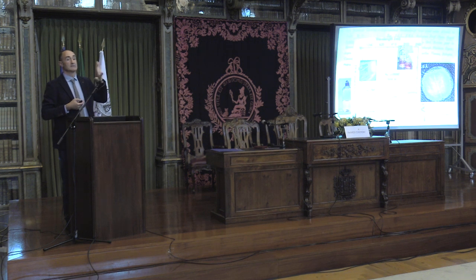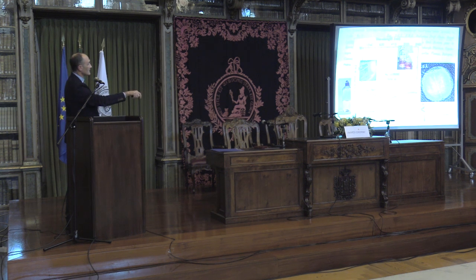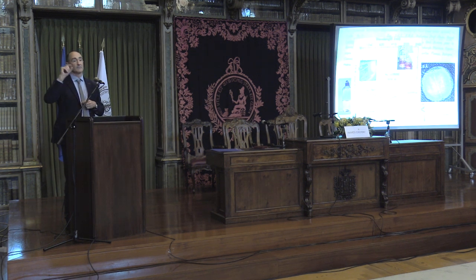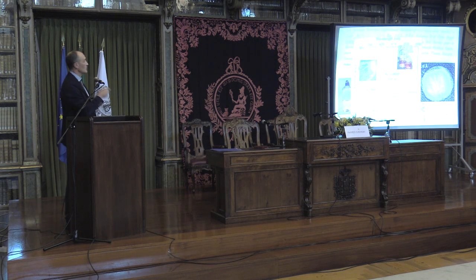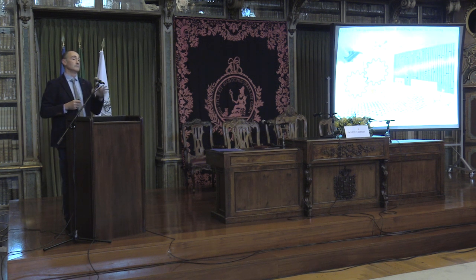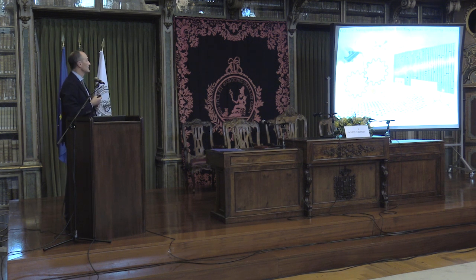So these are true size effects, which have nothing to do with the chemistry of the material. And actually, this is what I try to show in this picture here. If you take one of the particles from the bottles of Faraday and take it to an electron microscope, if you measure the lattice constant, you will find exactly the same lattice constant as you find in bulk gold. So the only reason why these colors are completely different, coming from exactly the same material, are the dimensions of the material. Okay, so we work on trying to improve what Faraday started 150 years ago. So we do a lot of, again, wet chemistry to grow metal particles.